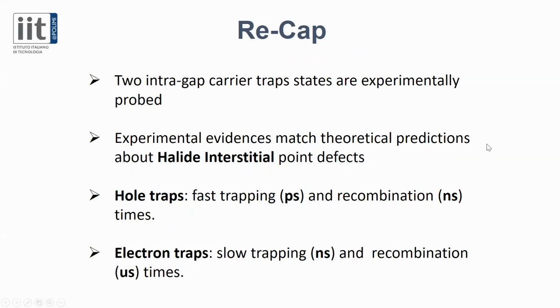lifetime. So to recap, what we know about these materials is that they have intra-gap carrier trap states that have been experimentally proved. They are related to the halide interstitial point defect, and they have a peculiar characteristic. They can trap holes with a very fast trapping and recombination time, or they can trap electrons with a very slow trapping and recombination time. Of course, these states all belong to a halide interstitial, but to a halide interstitial with a different oxidation number. So they are not, of course, exactly the same thing.